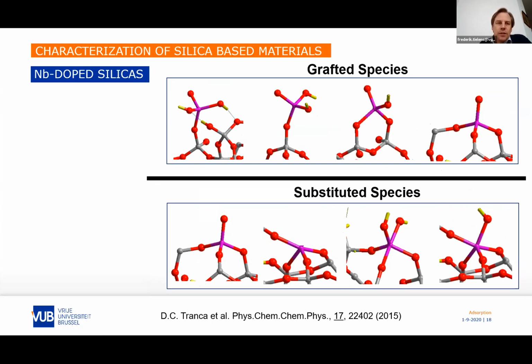Another example is niobium. Niobium silicas have also found a lot of applications in catalysis, and there we have both types of species: the grafted ones that we've seen before for vanadium, but also the substituted or inserted ones. So it shows much more links with the framework. And this was interesting because we studied, in fact, the effect of several sites together. What happens? Do they want to cluster, or do they want to be separate?